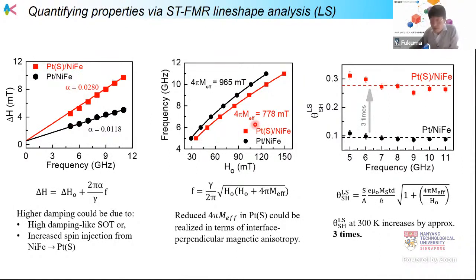This is due to the increase of the perpendicular magnetic anisotropy. Also, this is the conversion efficiency we estimated from the ratio of the symmetric component and the antisymmetric component. We can see here it's almost 3 times enhancement of the spin Hall angle from the platinum.